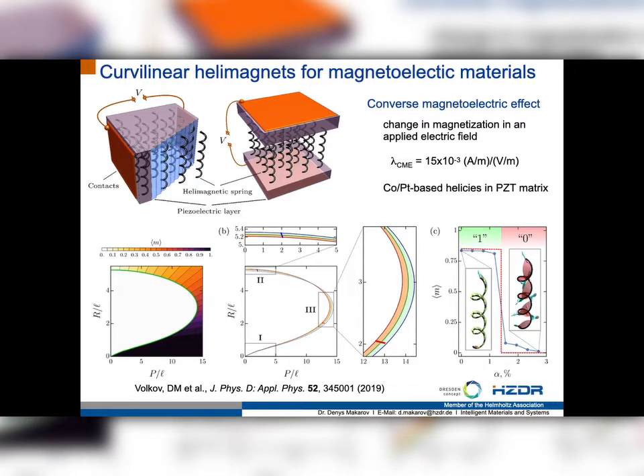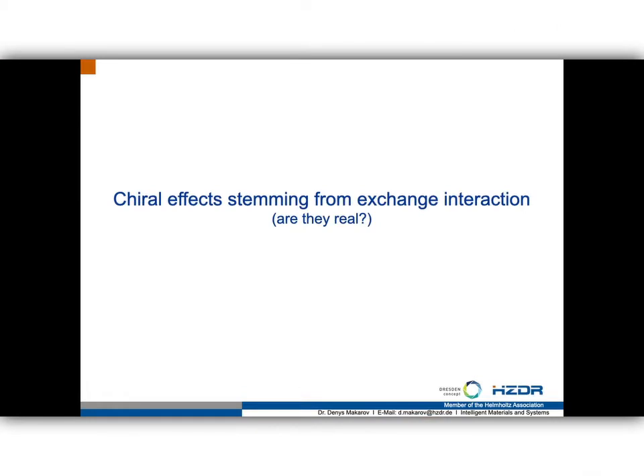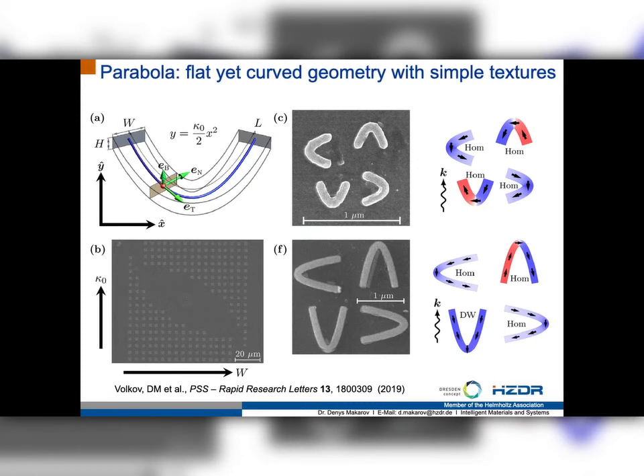Of course, all these predictions are very interesting only if you can confirm that these chiral effects which are coming from, let's say, exchange interaction are real experimental observables. In order to do such a verification, Alexei Volkov recently investigated switching of parabolas. So he took the simplest curvilinear geometry which you can imagine. It's a parabola, which is not only the simplest geometry, but it's also a geometry which has the simplest set of magnetic domain states. For example, you can get magnetization which is simply going along the stripe, or it can point, for example, in one direction.